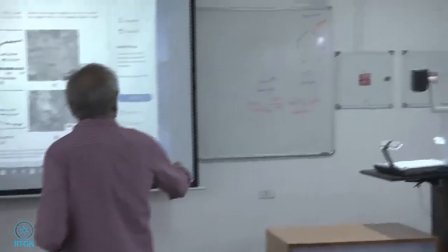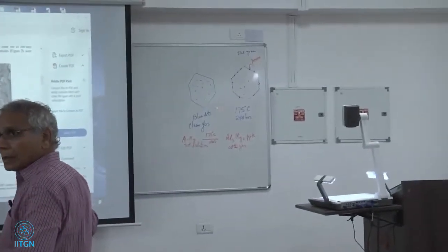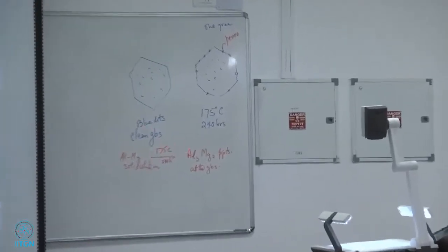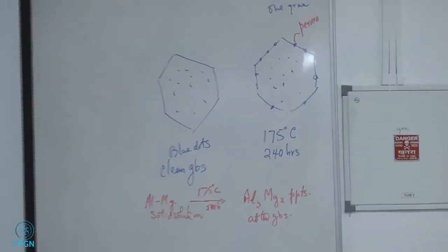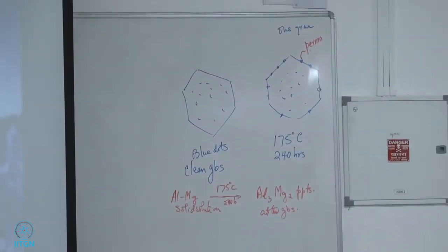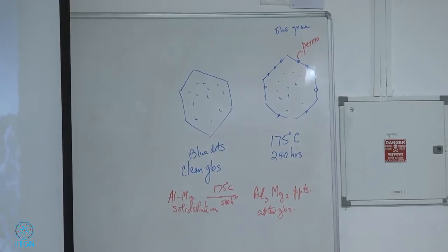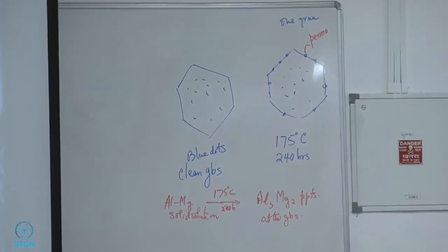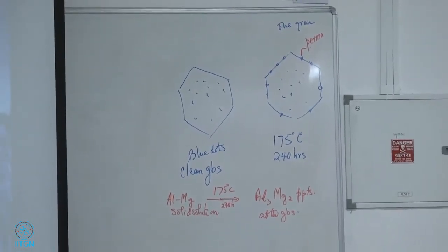The conclusion was these grain boundary precipitates will form. Okay? But maybe the ship will never go to 175 degrees C. Maybe it will go to 110 C. Well, even 100 degrees C is boiling water, right? So the only thing is the kinetics will go down. This guy, Tarun, got a little extra carried away. He put very high temperature, okay? Because he wanted to get experiments done within a reasonable time.